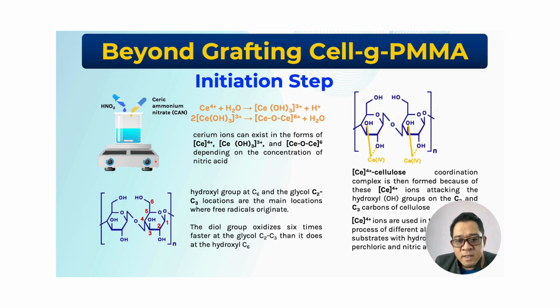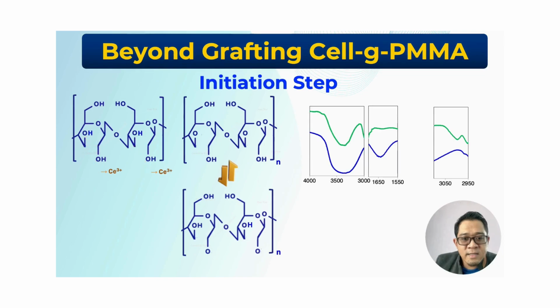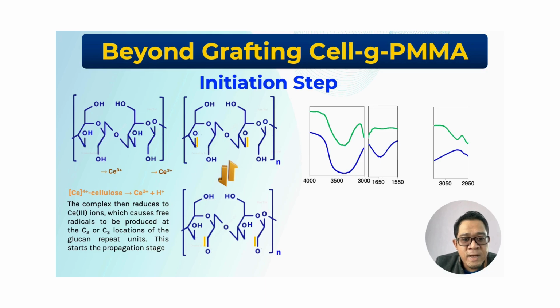And then, a Ce4+ cellulose coordination complex is formed because the Ce4+ ion attacks the hydroxyl group on the C2 and C3 carbon of cellulose. Ce4+ ions are used in the oxidation process of different alcohols and substrates with hydroxyl groups when perchloric and nitric acid are present. We can see that the Ce4+ cellulose complex is reduced to the Ce3+ ion, which causes the free radical to be produced at the C2 or C3 location of the glucan repeat unit. This starts the propagation steps.